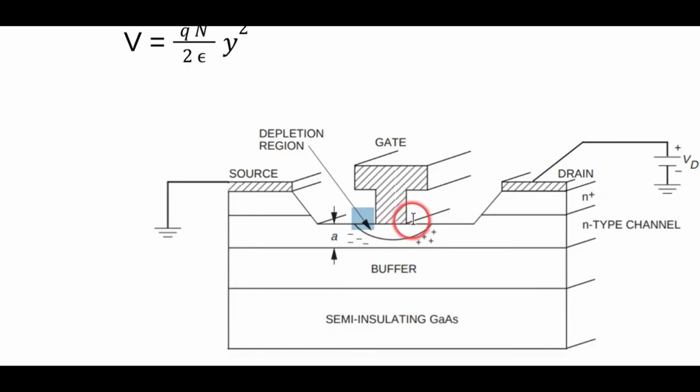There's dangling gallium bonds and dangling arsenic bonds. And what they do is they actually trap electrons. So underneath this gate, they form a depletion region. And you have to account for that when you're designing these active layers. You have to account for that depletion layer that's not there, because these electrons get squeezed through this little channel here as they go from source to drain, right?